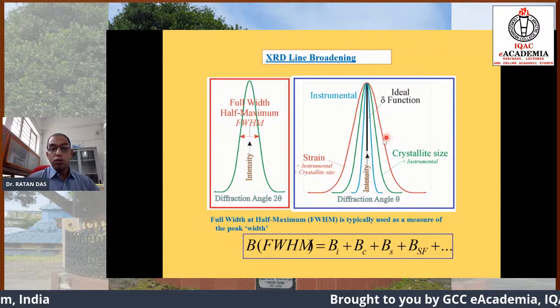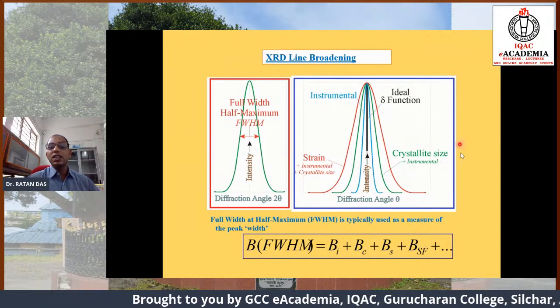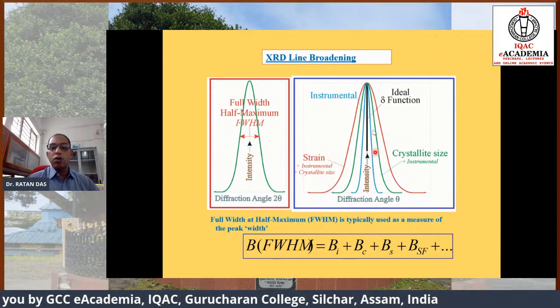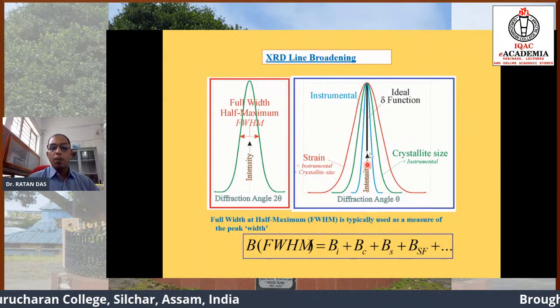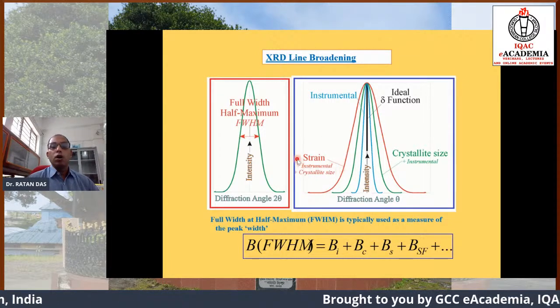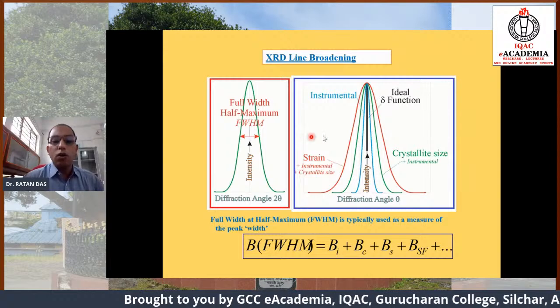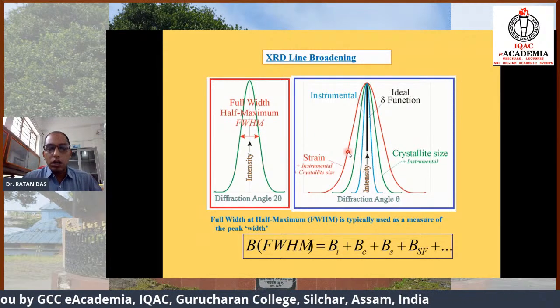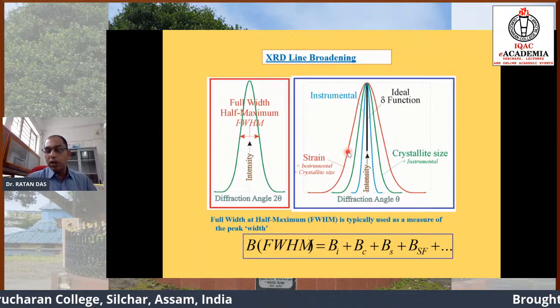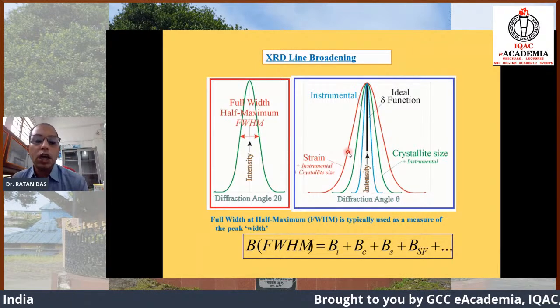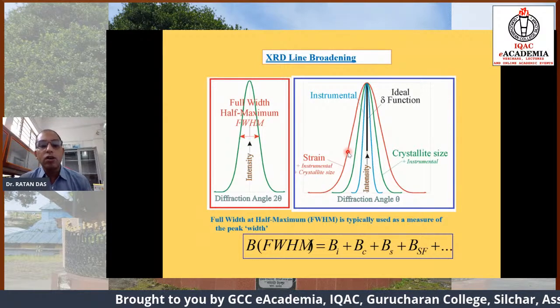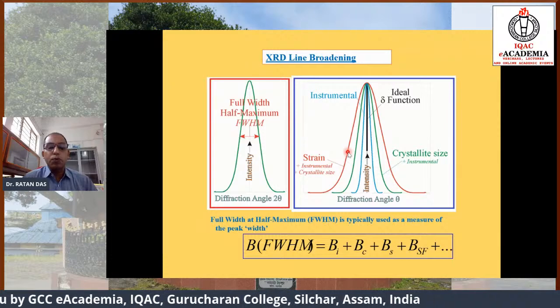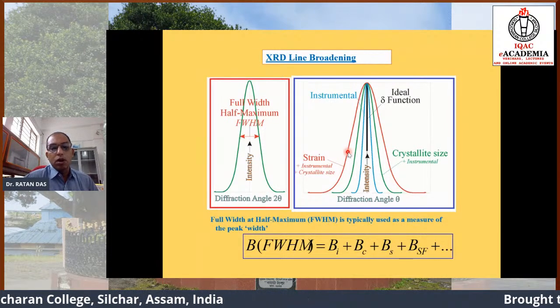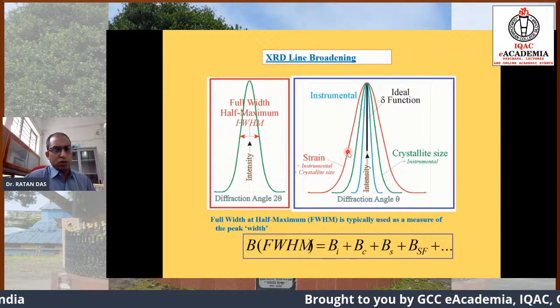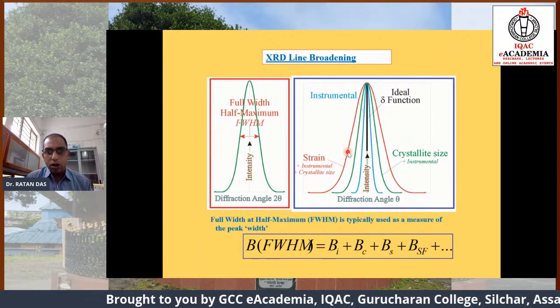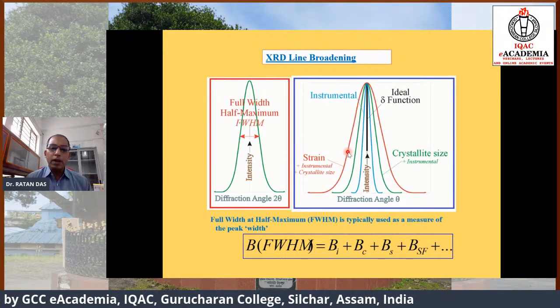But at the same time, I want to say that not only the crystalline size plays a role in broadening the X-ray diffraction pattern, but the strain also. I want to emphasize that strain also plays a big role in broadening, in nanocrystals especially. Why is the strain coming into the picture? It is not the external strain actually. When we prepare the nanocrystal, we generally confine the system in a very small range. Suppose we have a 10 nanometer nanoparticle. Then all the electrons, all the materials are confined in a very small place.